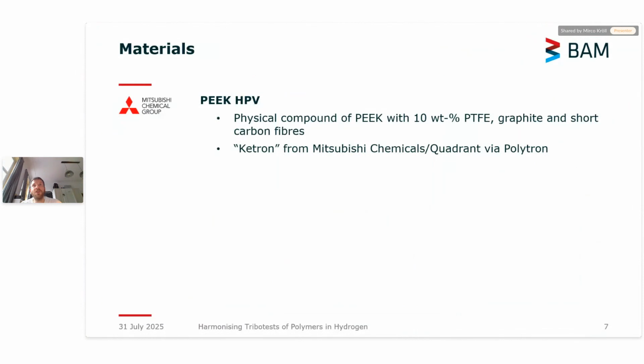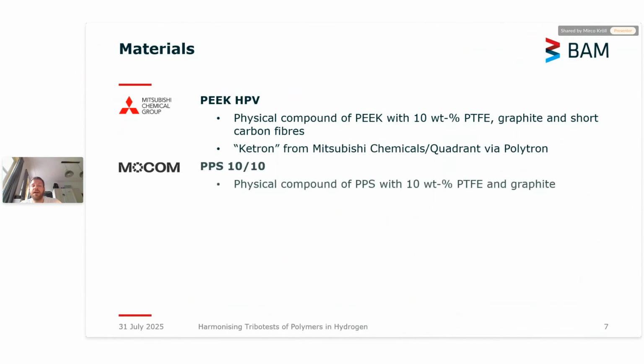The materials we used were commercial ones. The first one was a PEEK, provided by Mitsubishi, formerly Quadrant, which is a polyether ether ketone with 10% PTFE, graphite, and short carbon fibers. You can buy that. It's a commercial material.